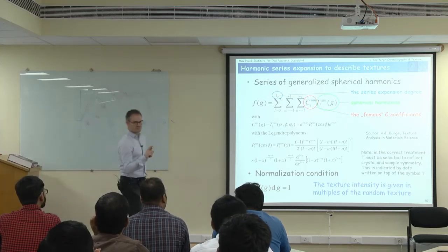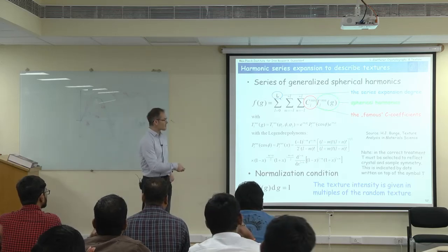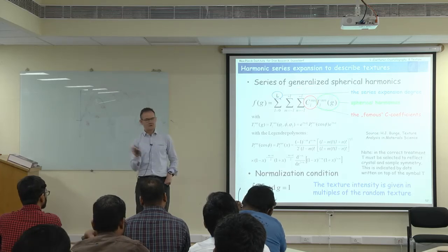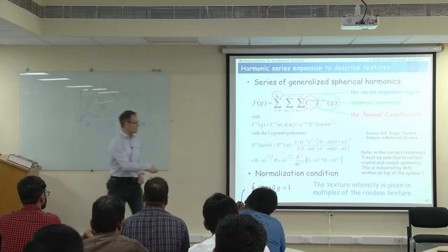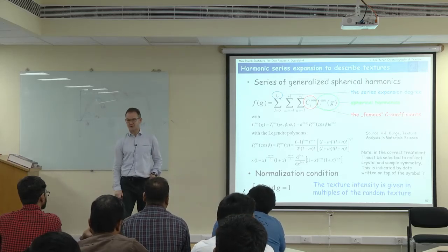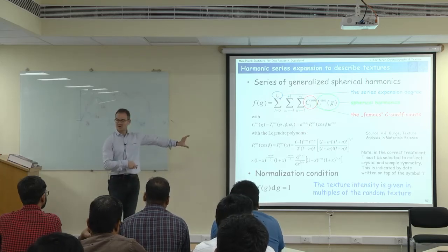Oh yeah, and then important: when you start writing it yourself, you will get into trouble. The generalized spherical harmonics are still something relatively simple to understand. But then you also have crystal and sample symmetry, and you need to involve the crystal and sample symmetry in these calculations. And then these calculations somehow modify in here.